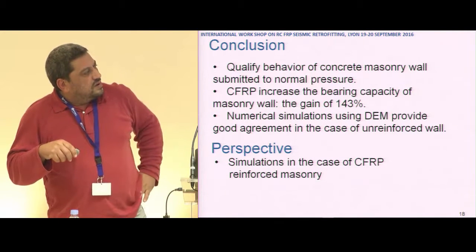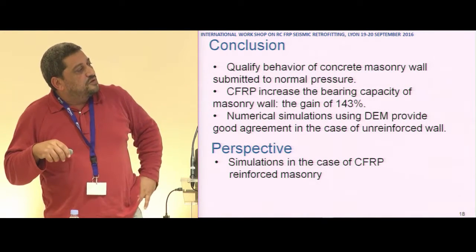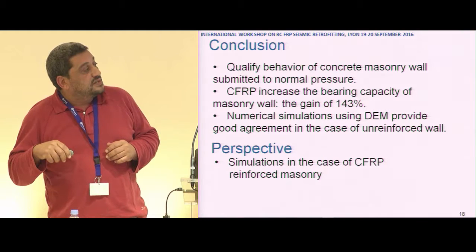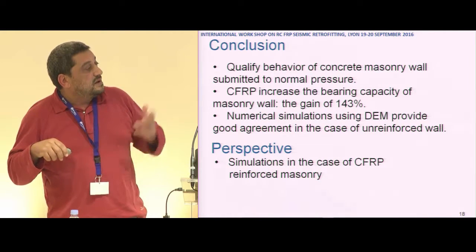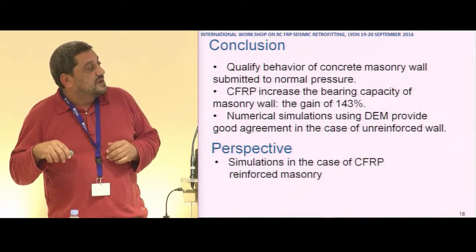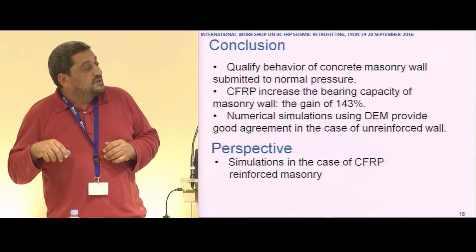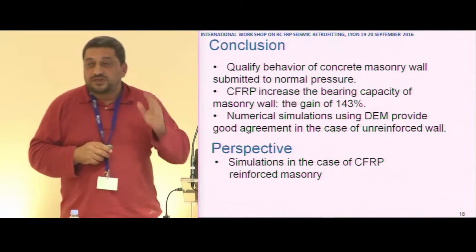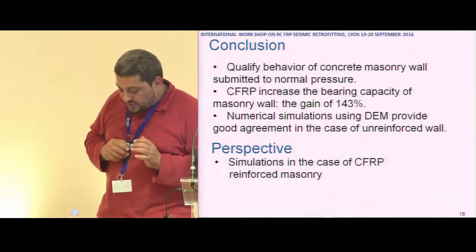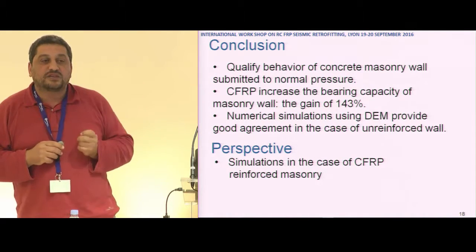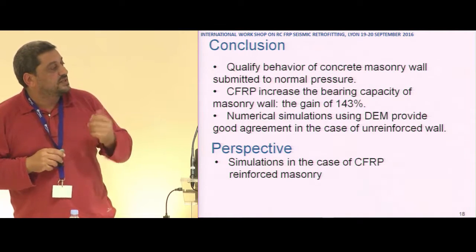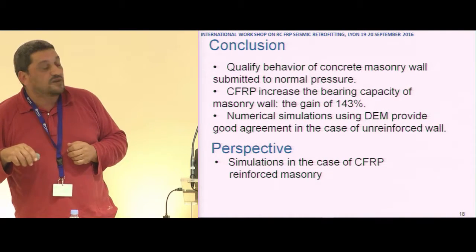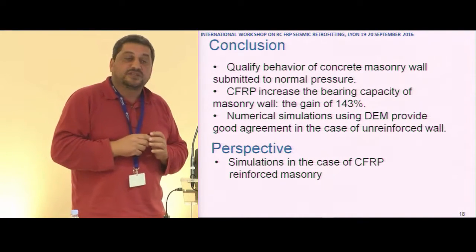Conclusion: we have characterized the behavior of concrete masonry submitted to out-of-plane pressure. We have shown that we can increase the bearing capacity — the gain can be 140%. Numerical simulation using the discrete element method provides good agreement for the unreinforced configuration, but for the reinforced configuration we need to work more to make the simulation realistic. The perspective is to simulate masonry with carbon fiber reinforced plastic using the discrete element method.